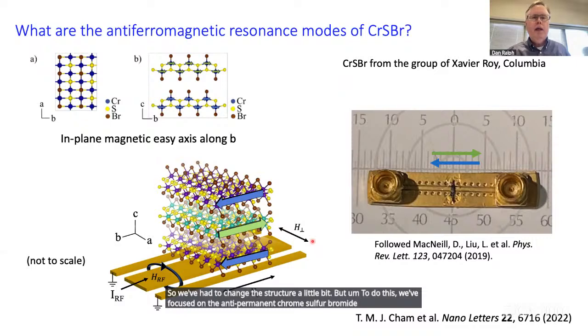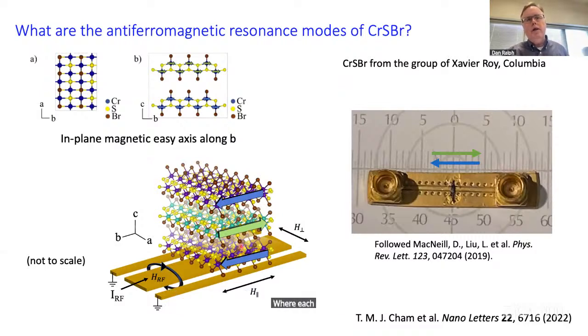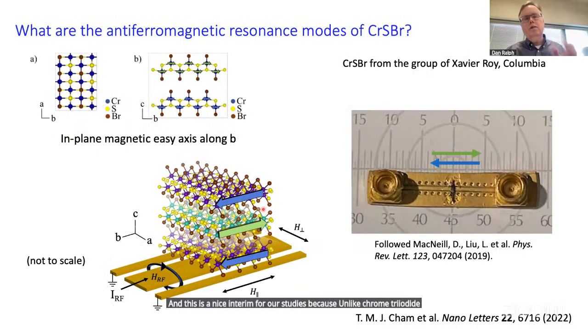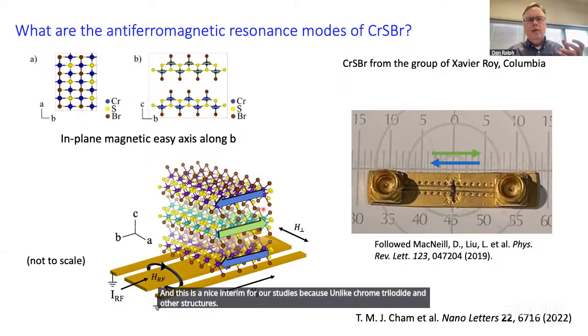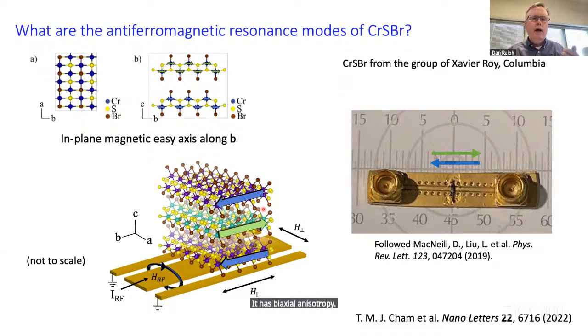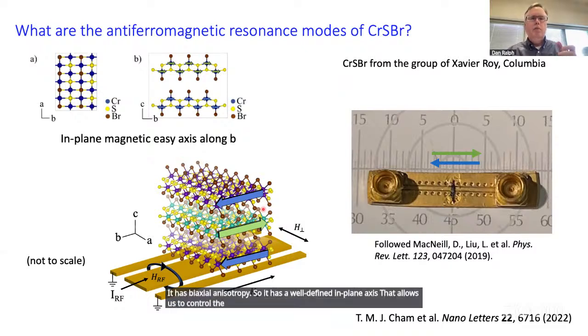This is an A-type antiferromagnet with in-plane magnetic anisotropy, where each layer is aligned antiparallel to each other at zero magnetic field. And this is a nice antiferromagnet for our studies because, unlike chrome triiodide and other structures, it has biaxial anisotropy, so it has a well-defined in-plane axis that allows us to control the directions of the moments a bit more easily than with chrome triiodide, which has very weak in-plane anisotropy.